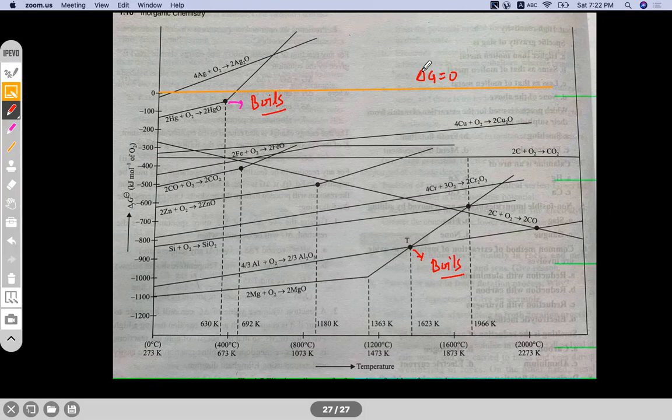Okay. Now the last property here: why will carbon have two types of graph? We have a graph here for carbon. One is where we have minimal or no change in delta G when it forms CO2. And then we have this negative slope, the graph goes down like this, when it forms carbon monoxide, that is CO. So write this down. I'll write down the carbon with oxygen on the next slide.